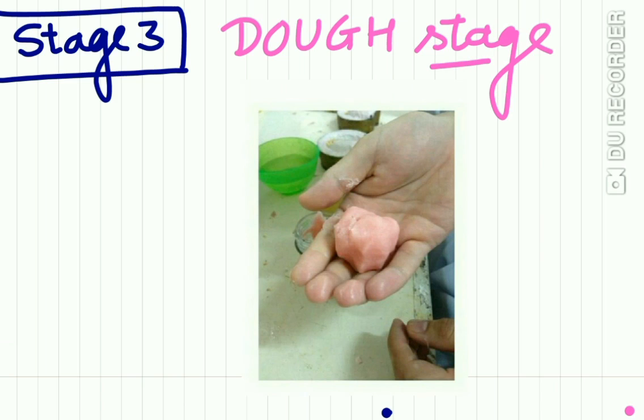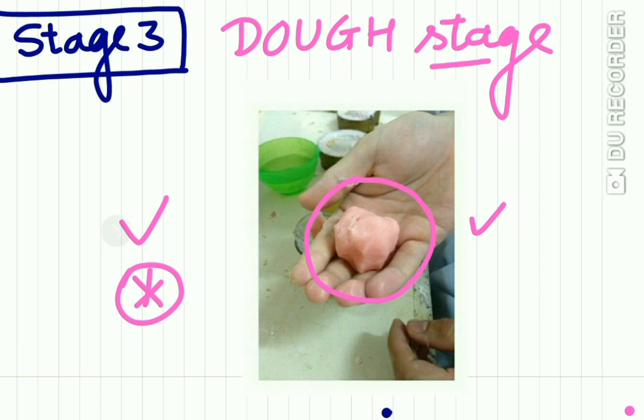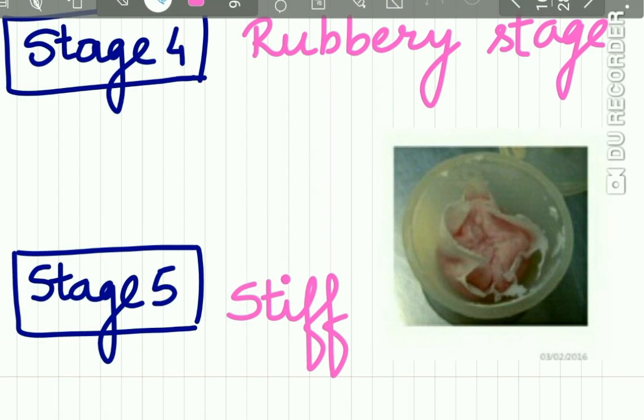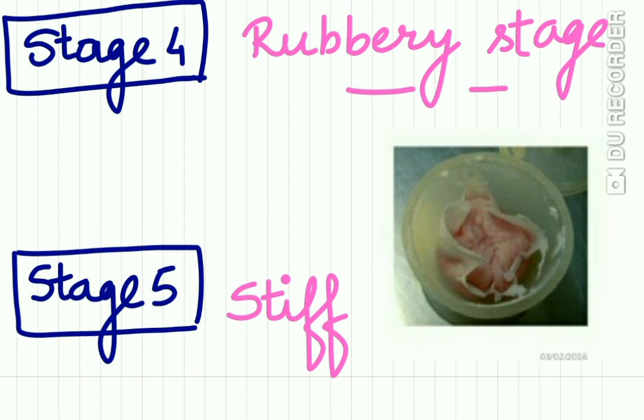Stage 3 is the dough stage, also called the gel stage — the mass is smooth and dough-like and does not adhere to the walls of the jar. Undissolved polymer particles suspended in a plastic matrix of monomer and dissolved polymer can be seen. Packing into the mold is done at this dough stage — very important. Stage 4 is the rubbery stage — the monomer disappears by further penetration, the mass is cohesive and rubber-like; it cannot be molded at this stage.